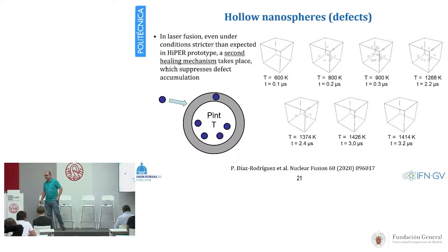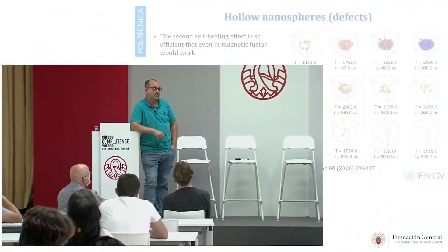Oh, I understand. It's only from the, let me say, doctrinal point of view that we always say energy is deposited in some amount, but what is important is not the amount of energy that is deposited. It's the form of the energy that is deposited, I mean the mechanism that can give rise to this energy. The mechanism of damage for neutrons is different than the mechanism of damage from charged particles. Yeah, right. Neutrons transmit a lot of energy, they interact producing very energetic primary knock-on atoms, we call PKA. And that has consequences because that produces cascades of damage. But as I showed here, even better here, this is very efficient in annealing out these defects.